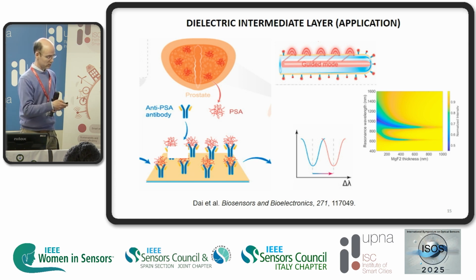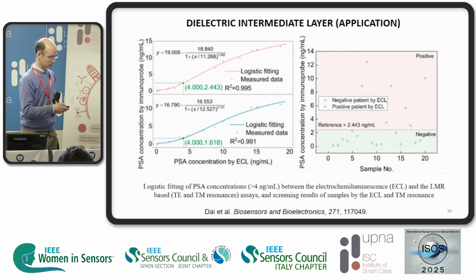Here I show this work because it's worth mentioning. This was by a Chinese group, Dai et al., in Biosensors and Bioelectronics, and they use the same structure you see here. So they obtain the same wavelength shift. The intermediate layer here is magnesium fluoride, and they could detect PSA, which is a biomarker for prostate cancer. I think this work is quite interesting because they experiment with human patients, and they compare their data with electrochemiluminescence, which is an older technique, and the results they get are quite similar.